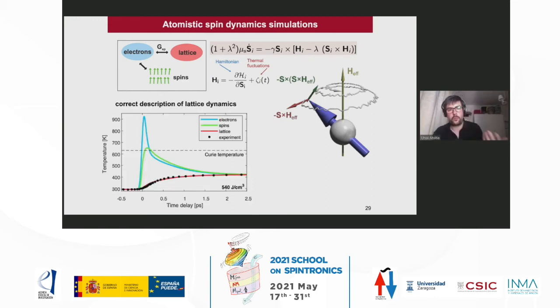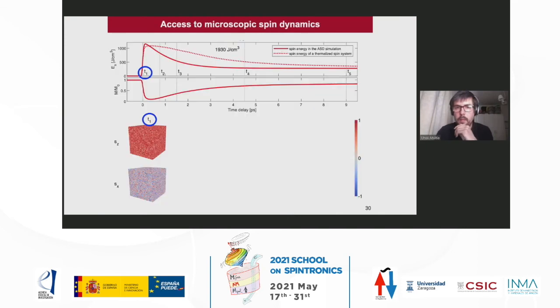With this model we can also describe correctly the lattice dynamics. Here you see the red line is the theory, and the symbols are the experiment. We can describe this and also get access to the microscopic spin dynamics. Here we see how the energy of the spin system evolves - this solid line shows that when we apply the femtosecond laser pulse, the spin system increases in energy.